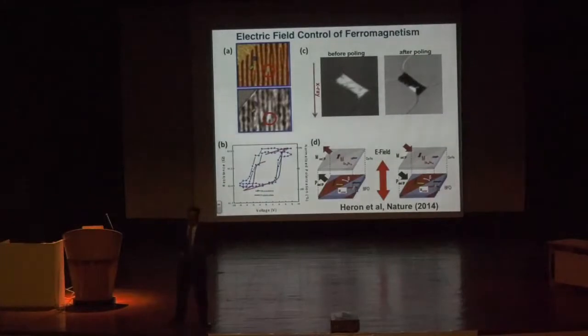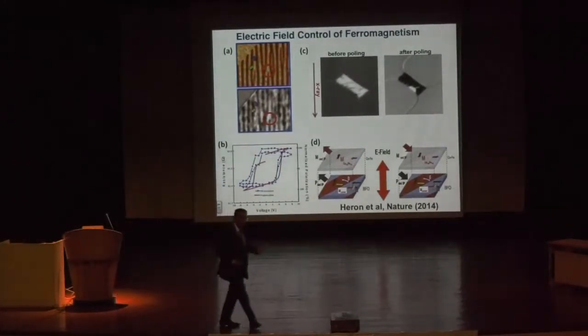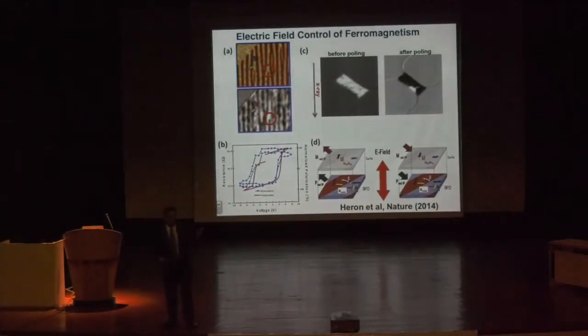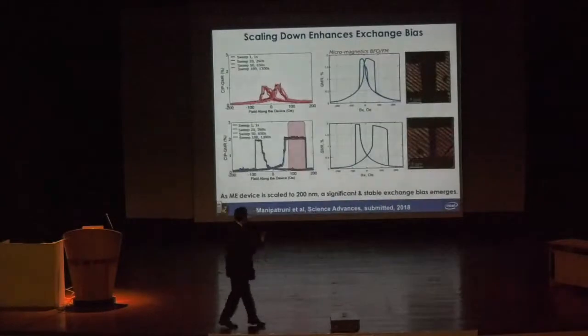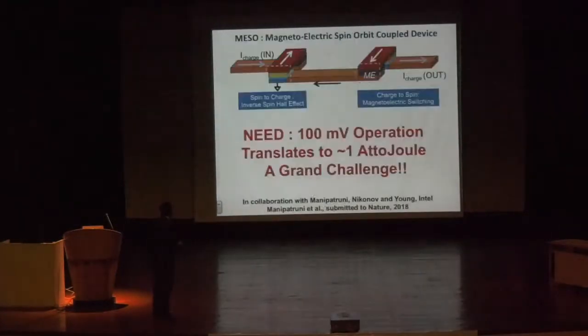And so we went back, did other measurements, ferromagnetic resonance measurements, to truly prove to ourselves that we are switching the direction of the magnetization by 180 degrees by switching the polarization by 180. Okay? That's shown here schematically. Here, it's a little bit more complex, with arrows going back and forth, but trust me, it's telling you that the canted moment in the bismuth ferrite is doing from this to this, and the ferromagnet is doing the same because they're coupled to each other. They're exchange coupled to each other. Okay. Oh, this is going too fast.